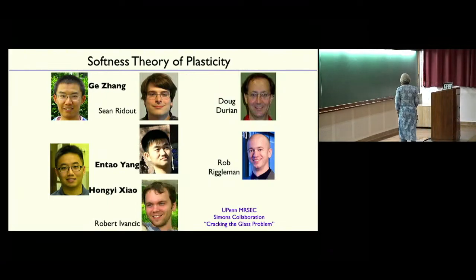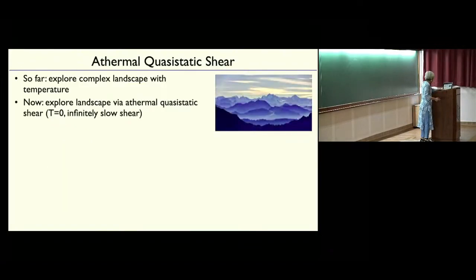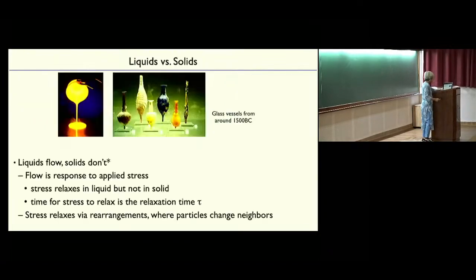This is the softness theory of plasticity, and we have a paper that was just accepted in PNAS about this. So now I'm going to think about dragging ourselves through this landscape, or really deforming the landscape, so that you can tip from one minimum to another. You deform it so that you can go from one minimum to the other without ever going over an energy barrier. So this is doing this at 0 temperature, so I'm always sitting at a minimum, okay? And shearing infinitely slowly, athermal quasi-static shear, okay? So that's a different way to explore this landscape.